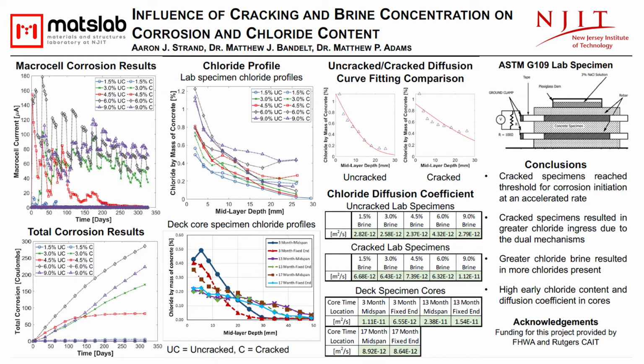The largest current result collected from the uncracked specimens reached a value of 1 microamp, which is 10% of the 10 microamp threshold value. The small values and fluctuations are likely due to the sensitivity and error within the voltage meter and testing setup. From these results, the corrosion potential of cracked systems is observed in general to be much greater than that in an uncracked system.